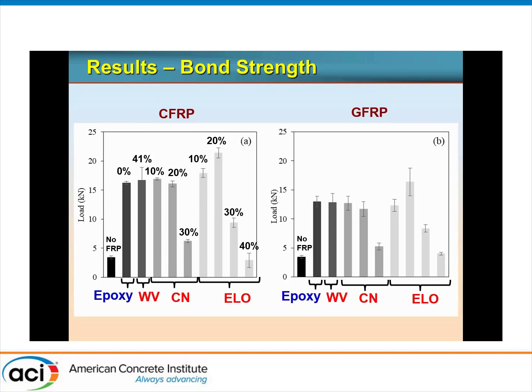Oh, I should also mention the repetitions were only 3, not 5, for the bond. So if you remove 1, the other 2 were biased. So I will take this one cautiously. I would say it's not any less, but I will not say necessarily higher. Again, at 30% and 40%, you can see the drop. I will show you the failure modes later. And the same story is happening for the GFRP.